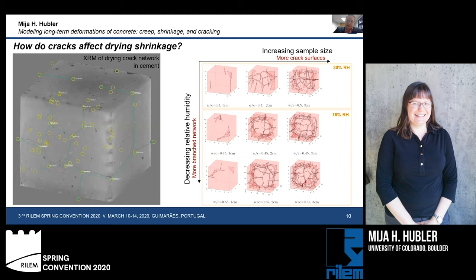Okay, so as we build a larger and larger structure, we can easily anticipate that there will be more cracks. The other thing that we find is that if we decrease the relative humidity, here going from somewhere around 30% relative humidity to 16% relative humidity, we consistently see that we end up with a more branched network. There is not so much of an effect from the water cement ratio in our samples.